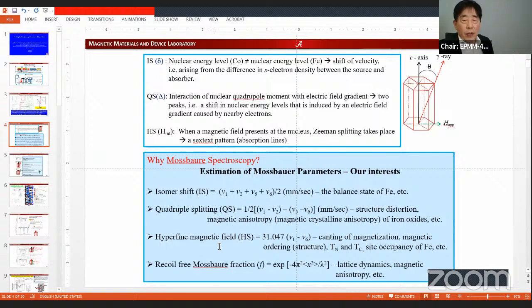Finally, a hyperfine field, we can calculate as 31.047 times the v1 and v6. If you have a big number for the hyperfine magnetic field, that means the magnetization of your sample is much bigger than for a smaller number for the hyperfine magnetic field.